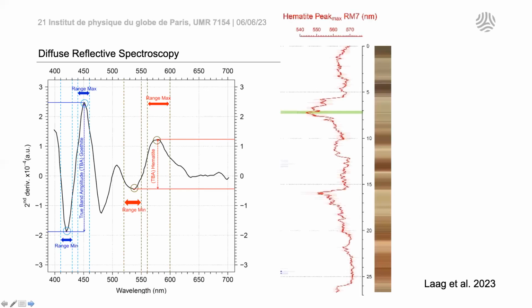Christian, in a recent paper in MethodsX, analyzed this in a very robust way, in the sense that he takes into account that normally it's a fixed wavelength that people use to determine the amplitude for your hematite. Knowing that the peak position shifts with respect to grain size and with respect to stoichiometry, using a fixed wavelength position can lead to results that are not as accurate. So he allowed it to scan and find the maximum and the true minimum, and that's why he called it the true band amplitude.